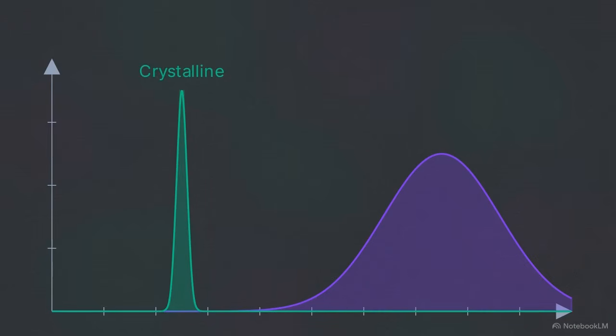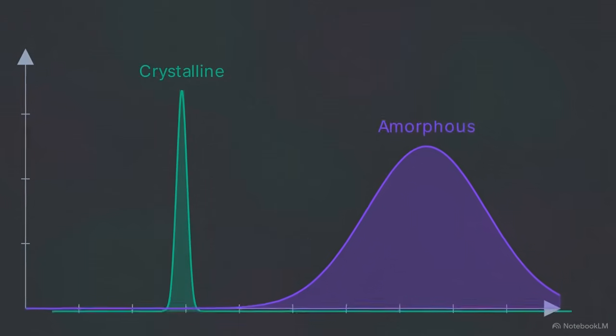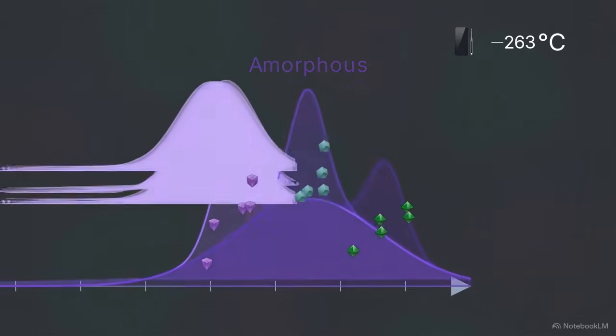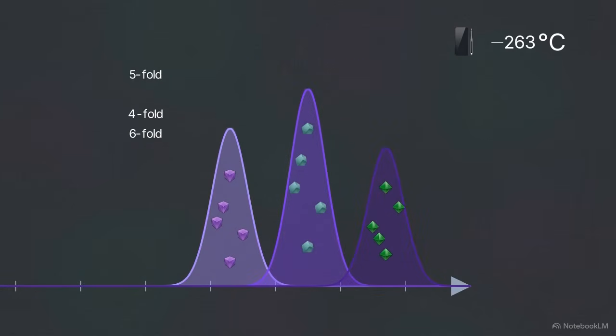Mapping the specific energy distributions reveals the subpopulations of structural environments hidden within the amorphous network. Crystalline references display sharp energy peaks, while the amorphous phases show broad, heterogeneous distributions. These broad distributions represent a variety of individual structural building blocks and the active thermal fluctuations in the glass. Lowering the thermal equilibrium to -263 degrees Celsius in simulation removes thermal noise. Distinct, isolated structural subpeaks then emerge.